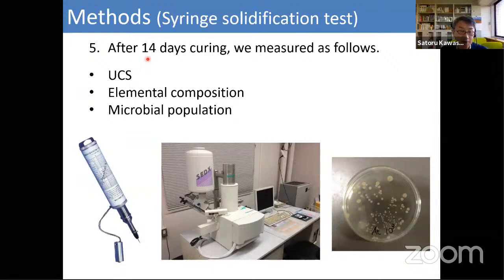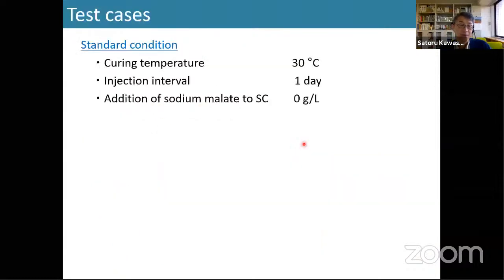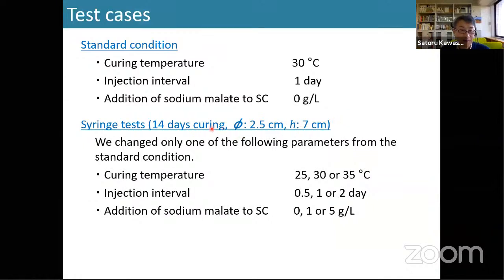Then after 2 weeks, after 14 days of curing, we measured the unconfined compressive strength, the elemental composition and the microbial population. This one is a testing case. For the standard condition, the curing temperature we fix at 30 degrees Celsius, injecting interval 1 day, and adding of sodium malate to the consolidation solution is 0. The first one is the syringe test, 2 weeks curing, around 2.5 centimeters in diameter and around 7 centimeters in height.